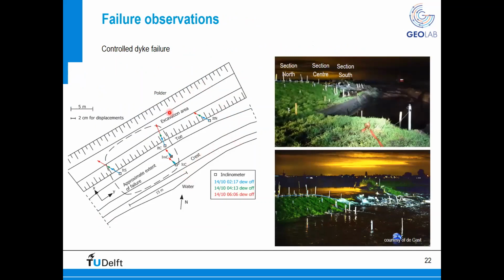So you see here that the failure was not extending throughout the entire longitudinal section, but was localized between the section south and the section center. And approximately it has an extent of 15 meters. The failure was composed of a 3D mechanism. So we have a lateral spreading at the toe of the dike, followed by an inward collapse of the crest of the dike. So you can see here a picture of the failure.